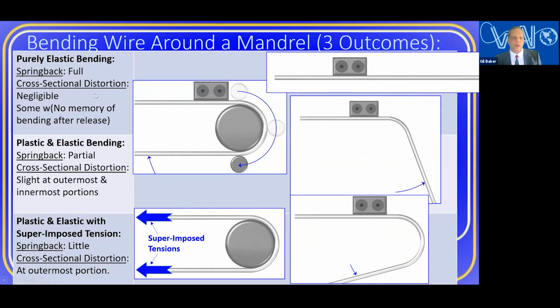180 degrees. Now, if the wire remains completely elastic in this process, when you release this fixture here, you're going to have the wire spring back as if nothing had happened. There's no history or memory of what occurred. It's going to look just as straight as it was here. However, if there's yielding, and that's mainly going to be given by the ratio of the wire diameter to the mandrel diameter, then there'll be spring back, but not all the way back to straight. There will remain a curve in the wire. Again, this curve is like the cast and bow we're talking about. But this is just for a sliding fixture.